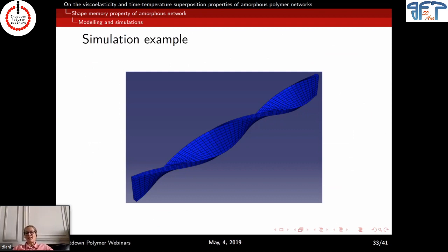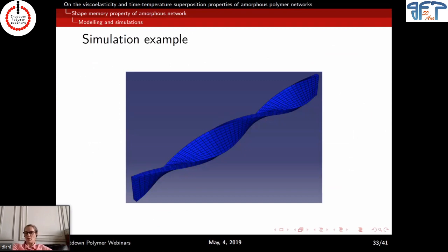And part of what I showed was also made on an epoxy network. So for us, the chemistry was not that important. We just needed a network, an amorphous network. Once we have an amorphous network, we are capable of characterizing the mechanical properties and then predicting the shape memory property, because that's not a special property of this material. It's just linear viscoelasticity, the viscoelasticity and the time-temperature superposition. Exactly. They should, if properly measured.